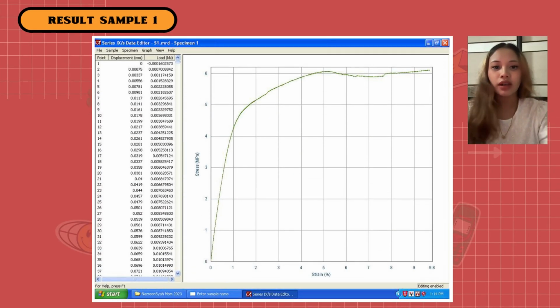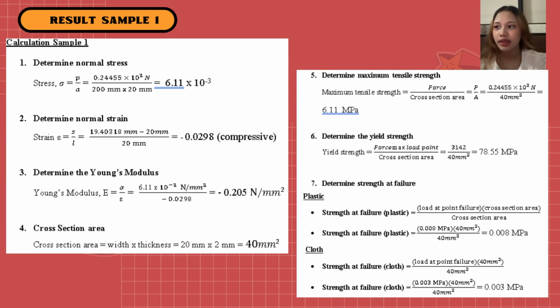So this is the graph for result sample 1. The highest load is 0.24455 kilonewton. The next one is the calculation result for sample number 1. The normal stress is 6.11 to the power of -3, and then strain is -0.0298, which is compressive. And then Young modulus is -0.205 Newton per millimeter square. Cross section area is 40 millimeter square. Maximum tensile strength is 6.11 MPa. Yield strength 78.55 MPa, and then strength at failure for plastic is 0.008 MPa, and for cloth 0.003 MPa.